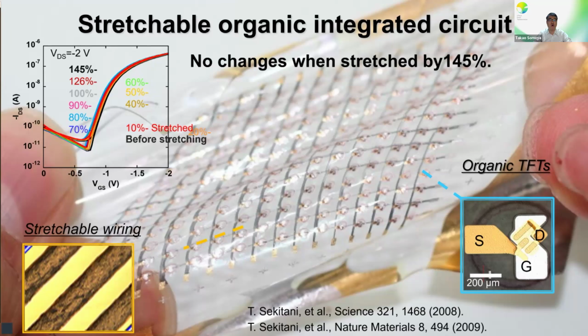Our approach is quite straightforward. First, we put the two-dimensional array of rigid islands that are embedded in the rubber substrate. And then we can print the organic transistors at the exact position of the rigid islands. And finally, source drain and other electrodes are connected by using an elastic conductor. So in that way, when we stretch our devices, all the strain is accommodated by changing the length of wires. Thereby, we succeeded in achieving stretchability over 145% without causing any degradation.